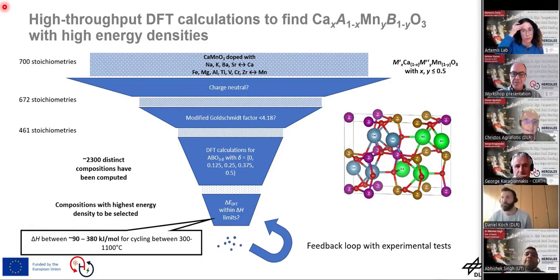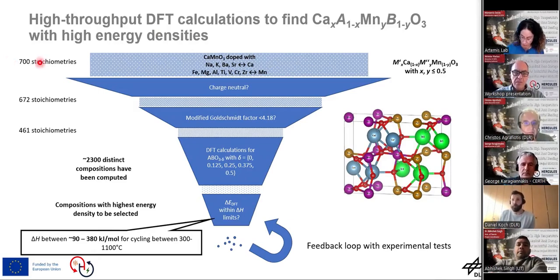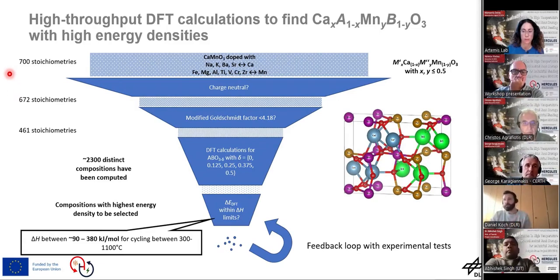So just in brief, we performed quantum mechanical calculations, so without the need for any experimental inputs. We took a base composition which we knew works well, which is calcium manganese oxide. And we have replaced some of the elements in calcium manganese oxide by other elements, and we have calculated the performance or the capability of thermochemical heat storage in these doped compounds. So we checked if they are charge neutral, if they are expected to be stable, and then we calculated the redox thermochemistry of these materials, for several thousands of compounds, and we could identify the ones which, from a theoretical perspective, are expected to be the most promising materials for such heat storage applications.